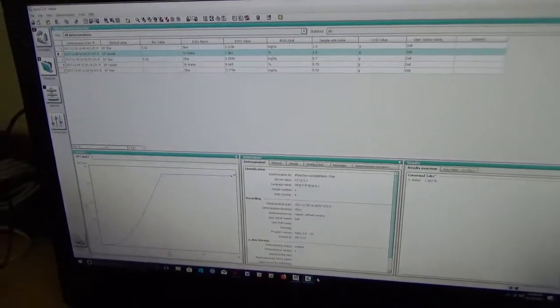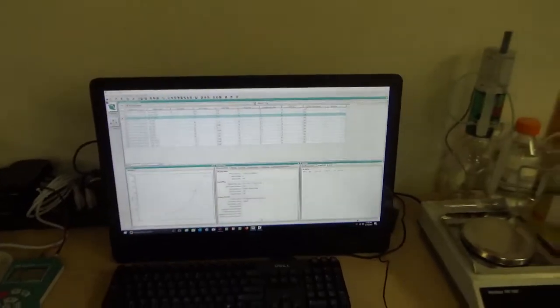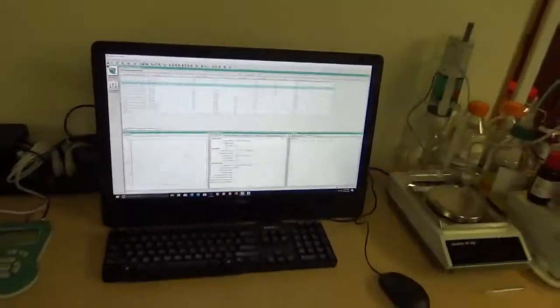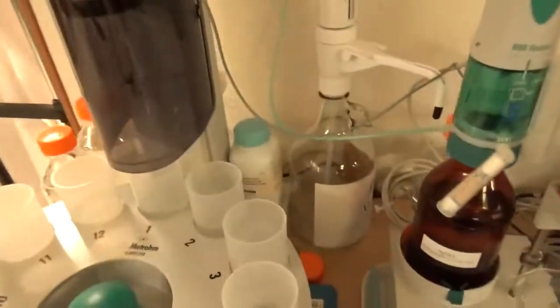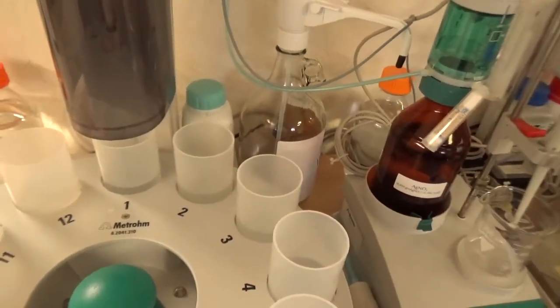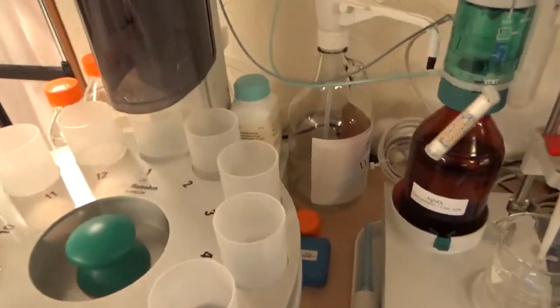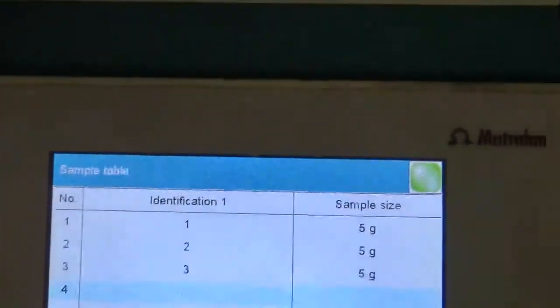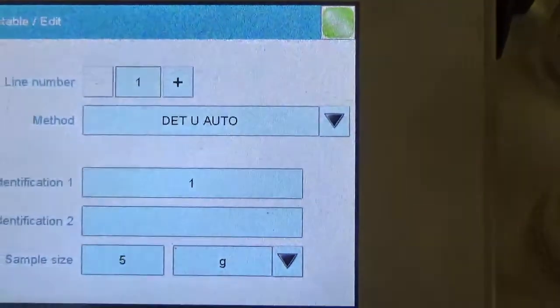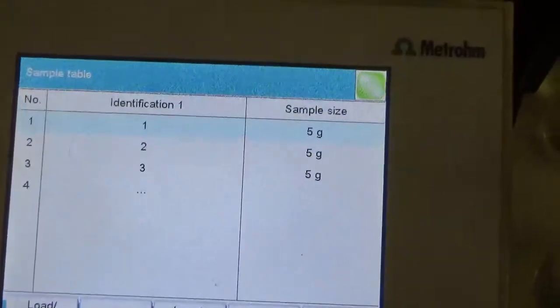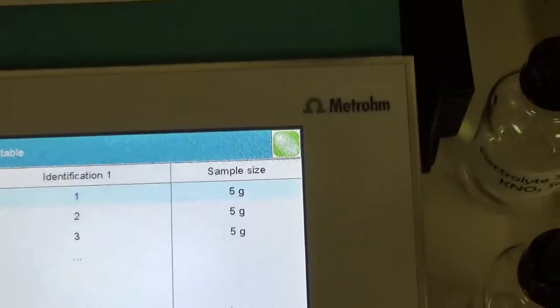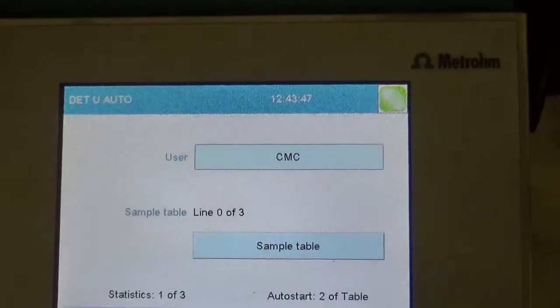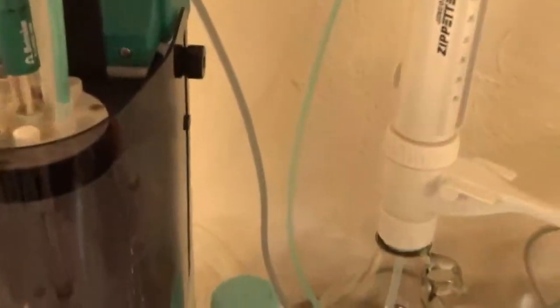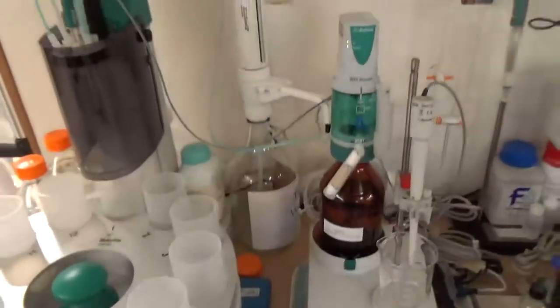So let me show you first how we do the potentiometric titration, which is the most common titration we do for chloride content, and how the data is collected in tiamo. To do the potentiometric titration, we collect the samples, we put the acid-soluble or water-soluble concrete filtrate in these Metrohm beakers, and then we insert the sample. We insert a sample table, and there we insert the data. I just inserted 3 samples where we give the sample weight and the method, everything. For each sample we can give the project number, the sample ID, the date the sample was extracted, all the information. After all the information is there, we have the electrode inside and the burette inside. Once everything is inserted, we just press the start button, and the titration starts.